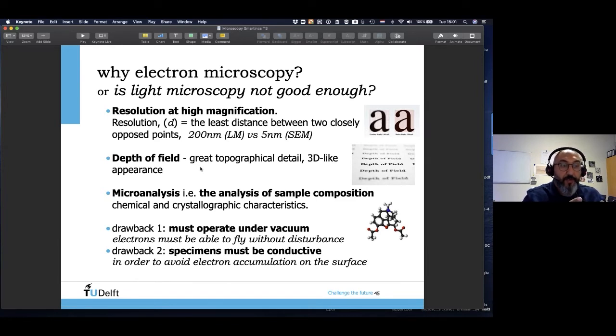But there are drawbacks, of course. Number one, you must operate under vacuum. That means sometimes it can be detrimental for your cement paste. Why? Because your cement paste can have a certain amount of water inside. If you evaporate that, if you dry it all the way, you might get cracks. And depending on your research, this can be detrimental or this can be negligible. It just depends on what you're looking for. But understand that you are generally operating under vacuum.